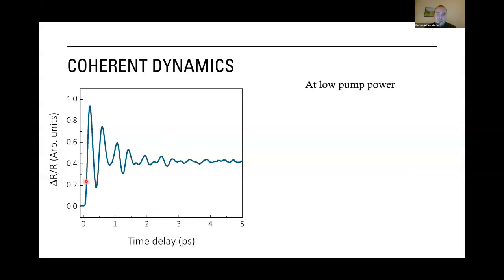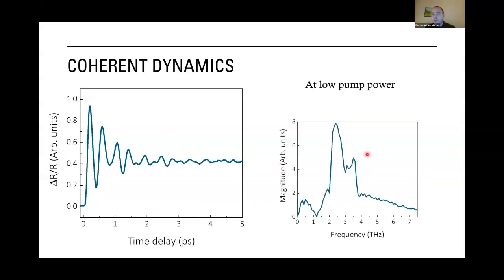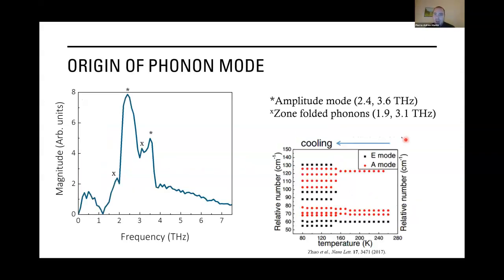And we obtained a beautiful coherent oscillation. And when we perform the spectra, we can see that it's composed of multiple vibrations. By comparing to Raman data, we were able to attribute these modes to zone-folded phonons. Indeed, when you have this formation of the Star of David, you are going to have additional periodicity, and you will have a folding of the acoustic dispersion relation that is going to lead to some zone-folded phonons.